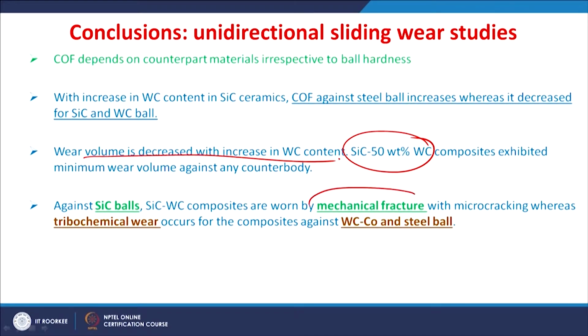Regarding the major mechanism of material removal, against silicon carbide ball, the silicon carbide tungsten carbide composites are worn by purely mechanical fracture with micro cracking, whereas tribochemical wear is dominating for the composites worn against tungsten carbide cobalt or the steel ball. So, there is a difference in the mechanism of material removal. So, there is a difference in the friction and the wear. So, this actually indicated very important information that when the silicon carbide tungsten carbide composites were subjected to different counterbodies, we have a different wear mechanism dominating. So, that results into the performance difference.